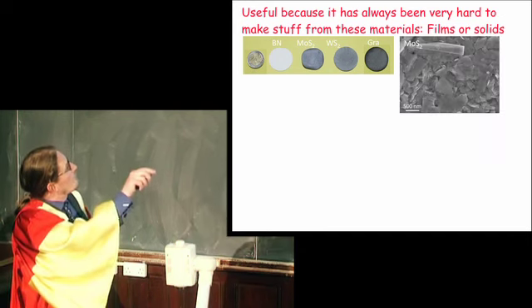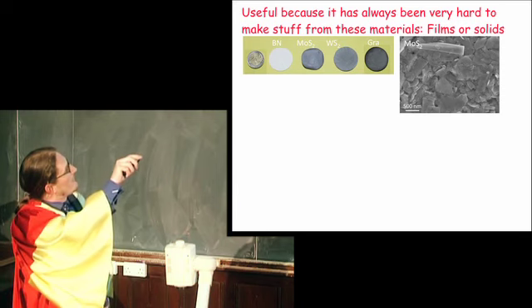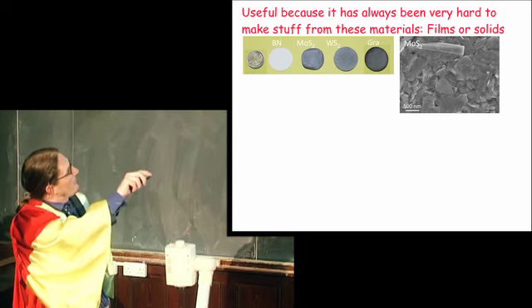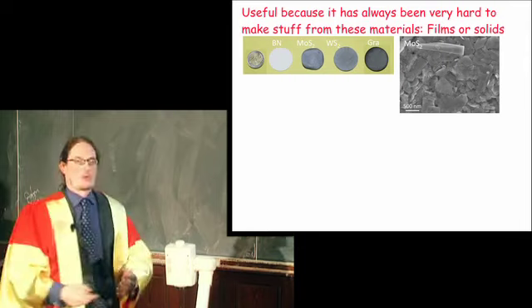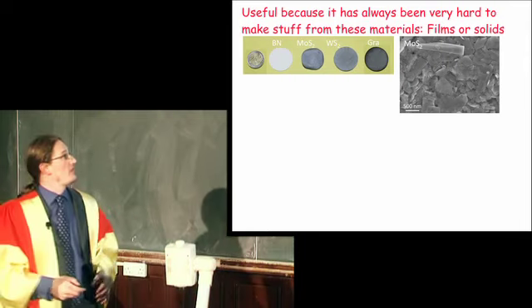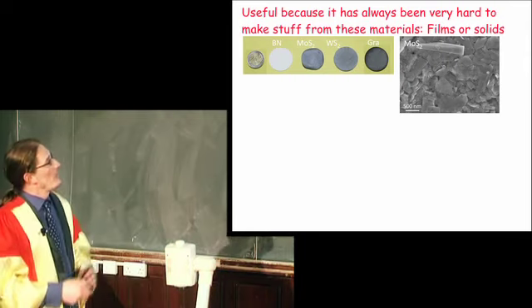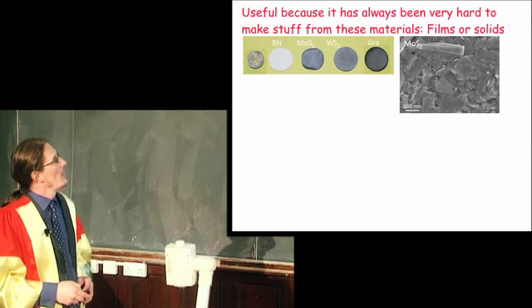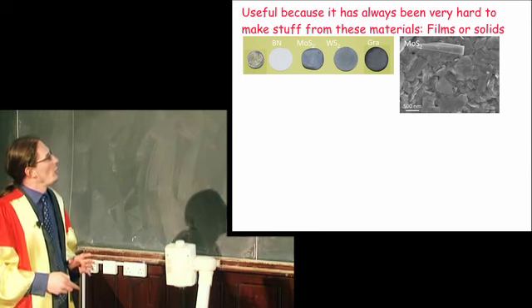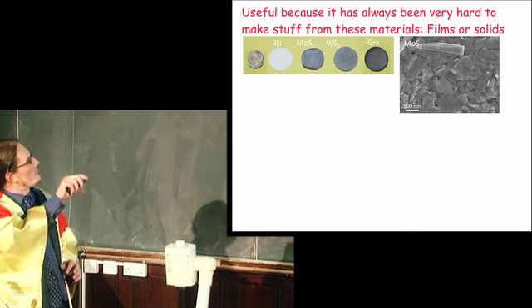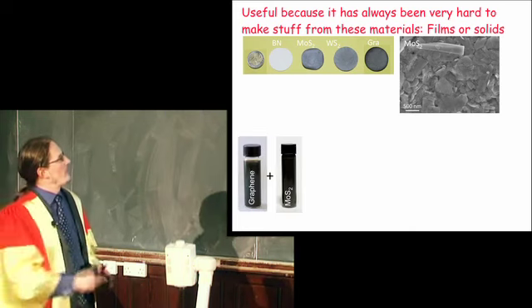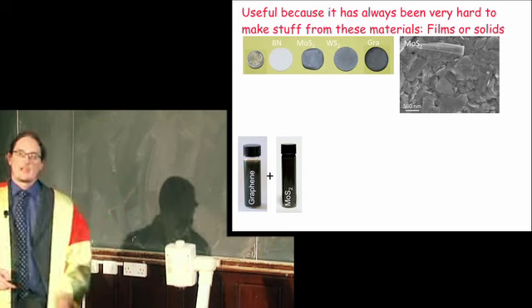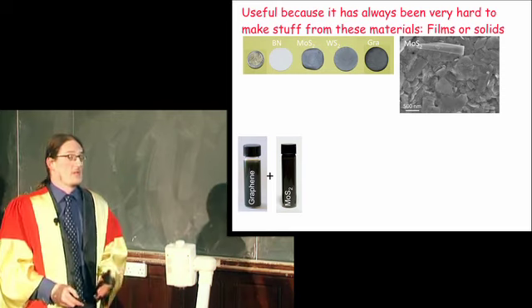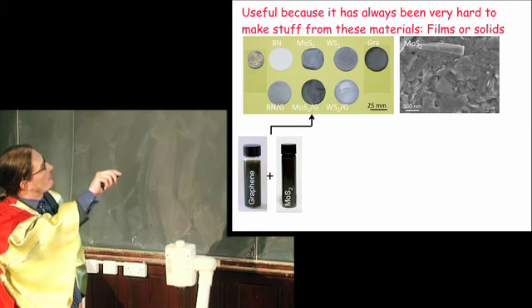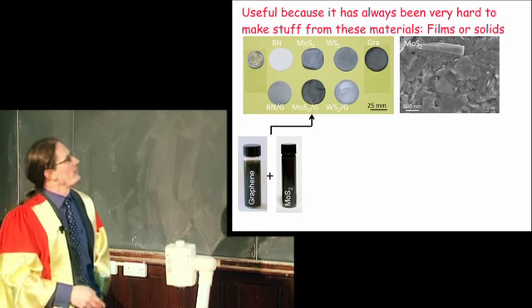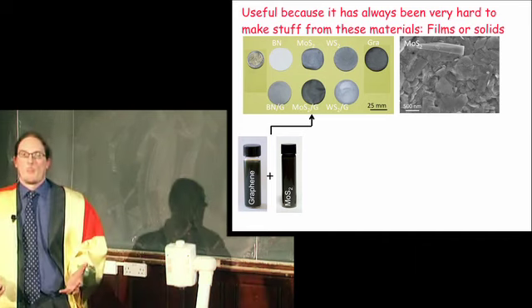Now, if you look with the electron microscope at the surface of these freestanding films, you'll see that they're just a disordered array of two-dimensional sheets. So, I mean, there's nothing fancy about them. One thing that is interesting, though, is that the solvents that you disperse these things in are the same set of solvents as you can disperse graphene in, or carbon nanotubes, or a lot of other materials. So that means you can take your dispersion of graphene, mix it with a dispersion of MoS2, and make a composite dispersion.